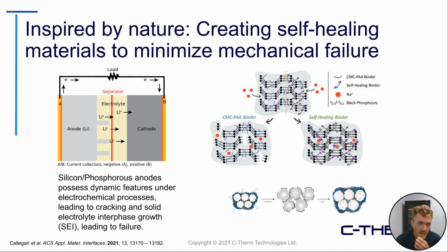Now, during dynamic electrochemical processes and under stress from mechanical vibrations, what can happen is that at the anode we can have small cracking, and this cracking and transfer through the electrolyte can create solid electrolyte interface growth, which grows from the anode towards the cathode, breaking the separator and ultimately creating a failure in the battery itself.